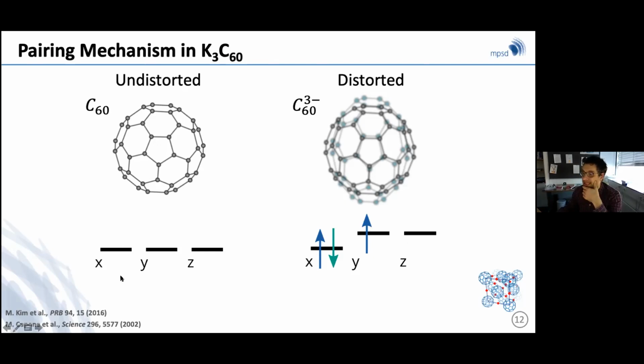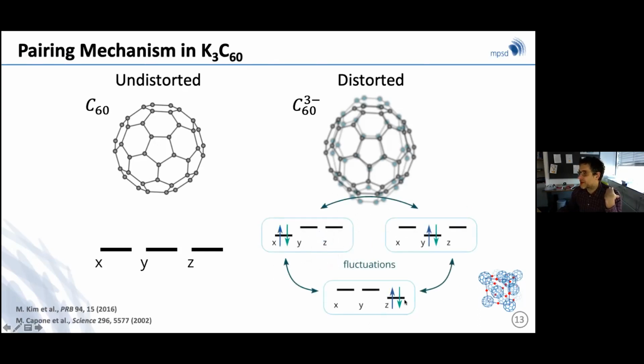And this is, of course, validated, for example, by NMR and by all sorts of measurements. This is a low spin state in which the singlet basically fluctuates between each one of these 3 orbitals, and it is assisted by molecular distortions. And it is believed that the orbital fluctuations that delocalize the singlet state around these 3 orbitals are the ones that ensure that this low spin state also generates a condensate and a superconductor. So this is by and large the modern theory of superconductivity in these compounds.